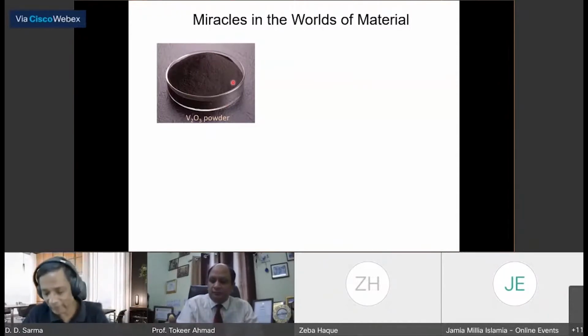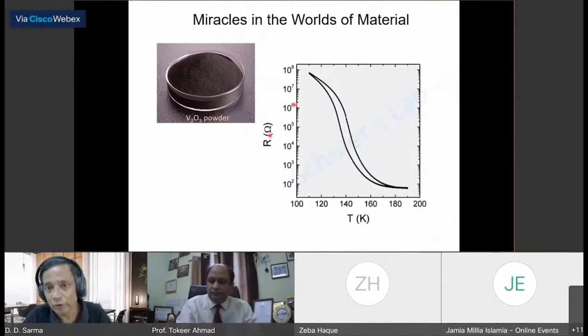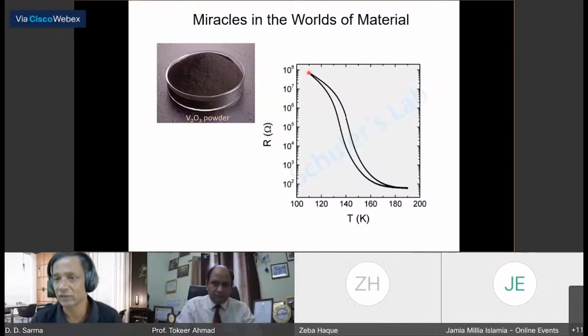This powder has this fantastic property. What I'm showing you is resistance as a function of temperature. Because, also, you know a metal is something that has low resistance and an insulator has high resistance. That is the most fundamental property that comes to mind when you talk about metal or insulator. This material at low temperature, let's say about 100 Kelvin, has a resistance of about 10 to the power 8 ohms, that is 100 megaohm resistance, for some particular shape and size of the sample.